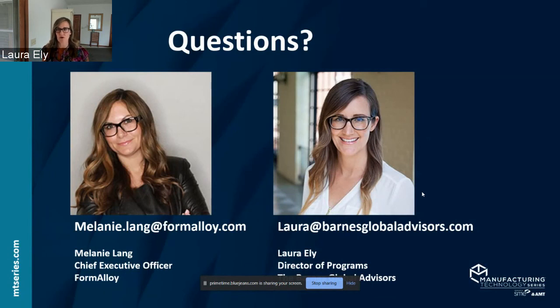The other thing is what type of flexibility you want to have on your melt pool. One of the reasons that we chose the laser was because we could change the spot size. If I wanted to go down and do a very fine melt puddle, like some of what Melanie is showing there, I could with my laser, because I could take the power down, I could change the spot size, I could do different optics. You don't necessarily have quite that level of flexibility to turn your melt pool up or down with some of the other arc-based processes. There's a certain limitation to that. So it really depends on your application and what performance and requirements you're looking to get out of it.